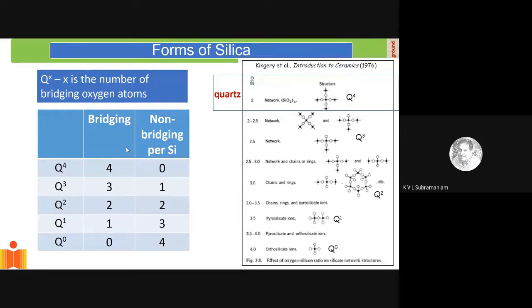So we have to learn to distinguish between the oxide forms of silica, and that basically takes us into silicon chemistry and silicon oxide forms. And this basically is quite complex. The silicon chemistry is actually quite complex. The way silicon combines with oxygen, it exists in different forms, as I'm showing on this table on the right hand side, and one has to develop an appreciation for these different forms. But one should be aware that there are inert forms of silica that are present, like quartz, and if that is present, then basically I cannot use it in any chemical reaction.